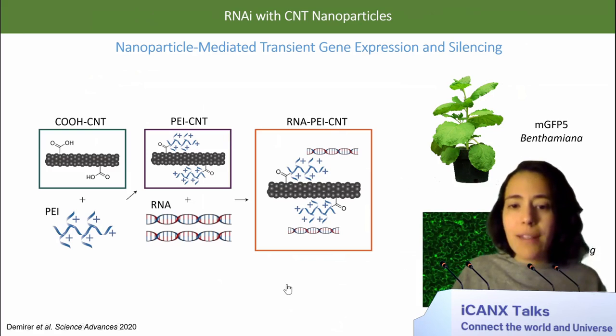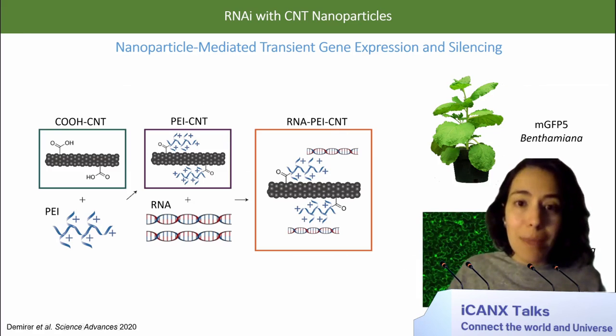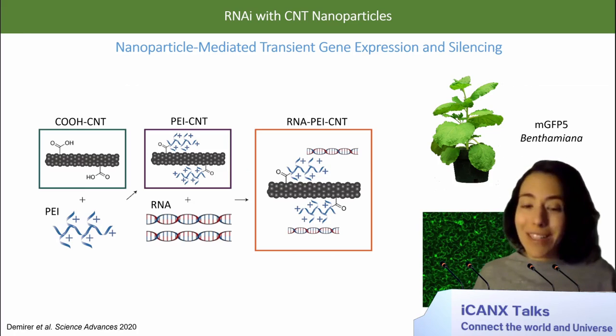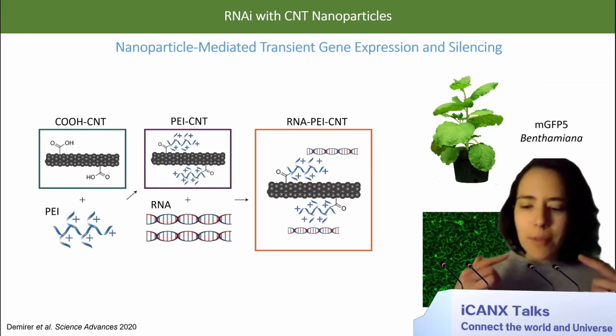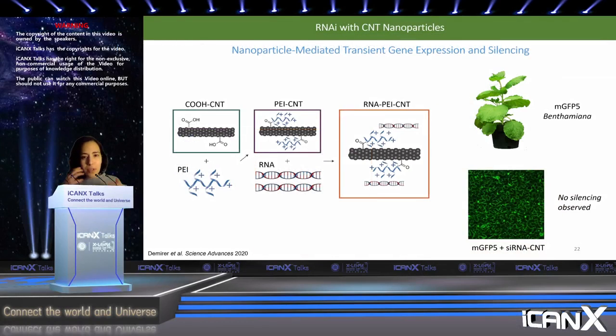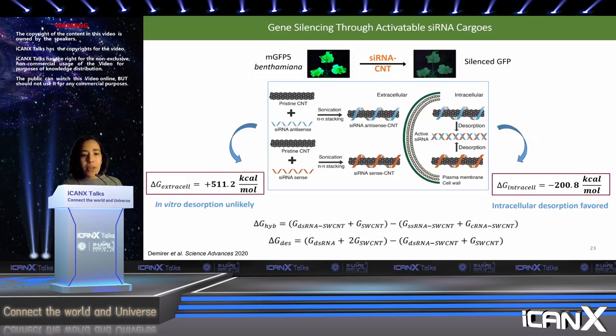However, when we infiltrated these constructs into our GFP plants, we did not observe any silencing of our GFP inside the plant tissue. And again, this was surprising to us because this is the construct that had worked so well for DNA delivery. We thought a little bit more about the chemistry and the motivation for developing chemistries of varying dissociation constants, and thought that since this RNA construct is relatively small and needs to be accessed by the RISC protein complex inside the plant for silencing, perhaps a looser association between RNA and carbon nanotubes was needed for this particular application. And so we performed a few thermodynamic calculations that suggest that this is indeed the case.